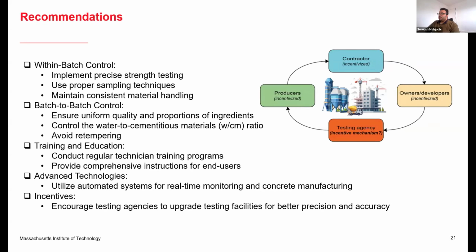And here are the recommendations from this study. By reducing the within batch variations and batch-to-batch variations, we could lead to carbon savings. We can consider precise strength testing, use proper sampling techniques, and maintain consistent material handling to improve the within batch quality and variations. And we can also reduce the batch-to-batch variations by ensuring the uniform quality and proportions of ingredients, and control the water to cementitious materials ratio, and avoid retempering.